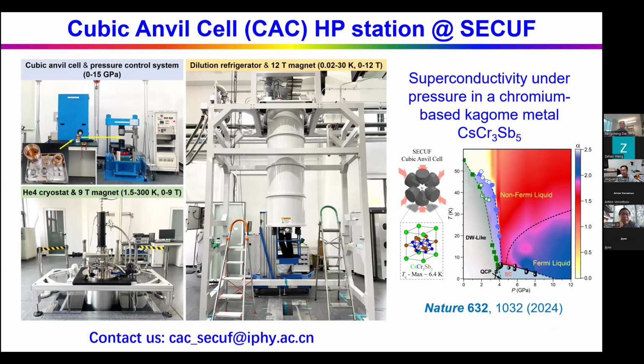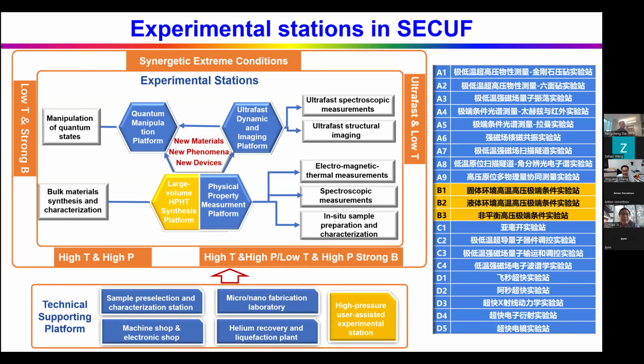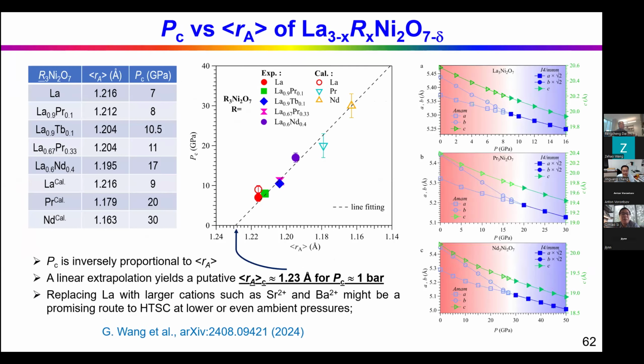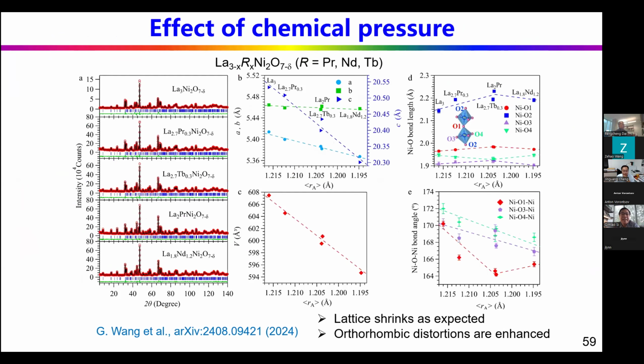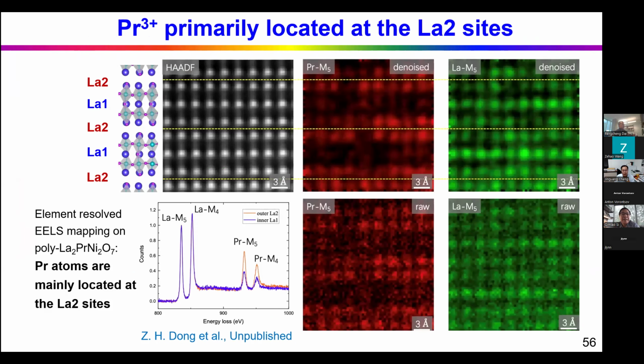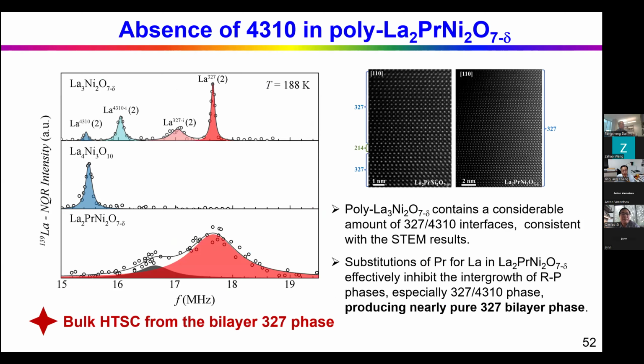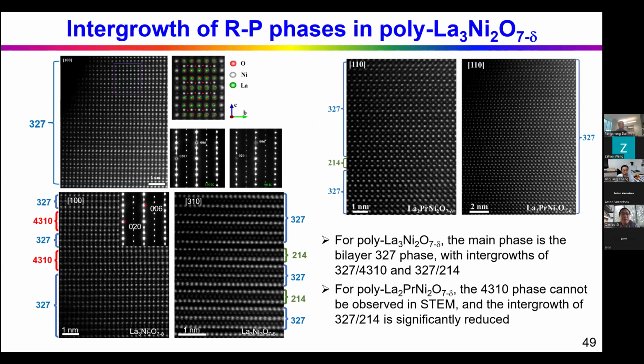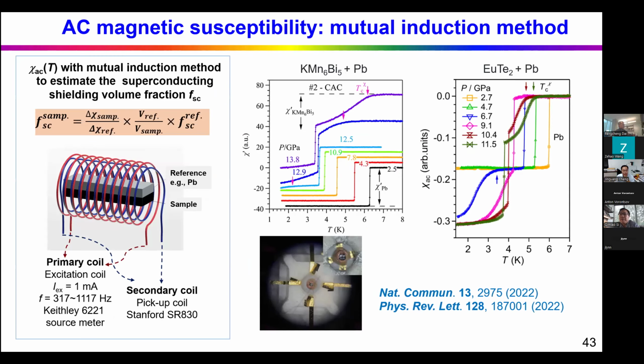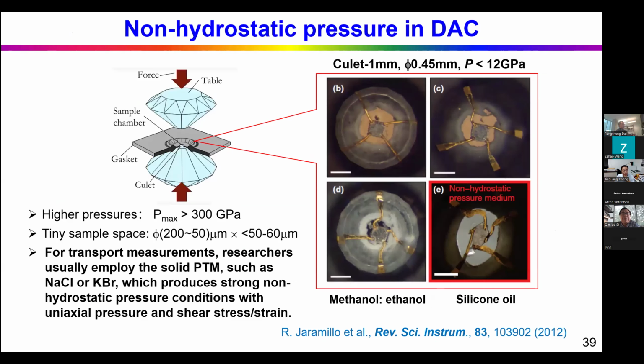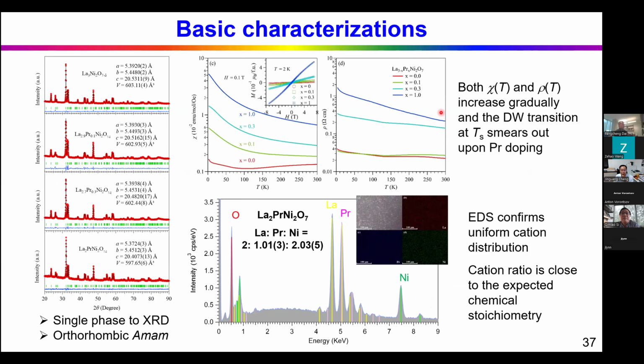So Jinguang, I was wondering, for the ambient pressure, are the properties of this praseodymium doped one roughly the same as the usual case, the undoped case? Actually, the resistivity increases by one order of magnitude. Let me show you. So here is the resistivity at ambient pressure. The red one is the undoped sample. With increasing doping, the resistivity actually increases. For this praseodymium doped sample, it shows a semiconducting behavior.